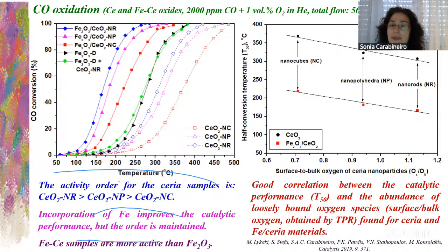Here we have a good correlation between the catalytic activity, its T50, meaning the temperature at 50% conversion, okay, half conversion temperature, and the abundance of oxygen species obtained by TPR. And we have here both for ceria materials and for iron ceria material. And we see that it's an interesting correlation.